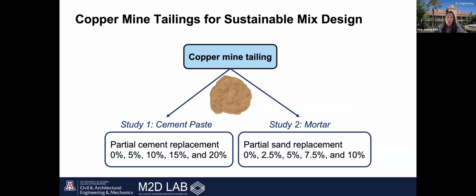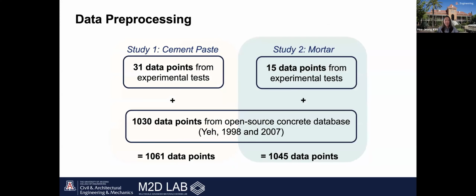copper mine tailings to develop sustainable mix designs. In the first, we used the copper mine tailings as a partial cement replacement in cement paste, and in this case, cement was replaced from 0% up to 20%. And second, we used the copper tailings as a partial aggregate replacement in mortar, and here sand was replaced from 0% up to 10%. And these two approaches help us understand how tailings affect the performance of different construction materials and how we can optimize their use for both sustainability and strength development.